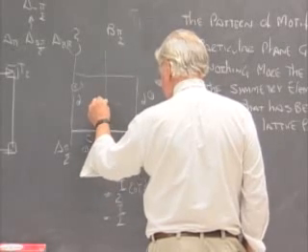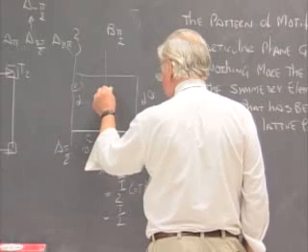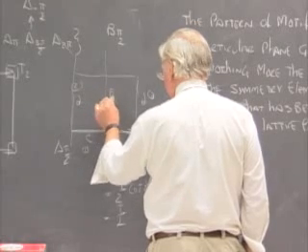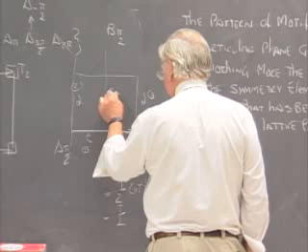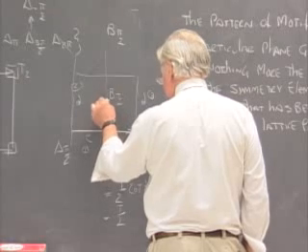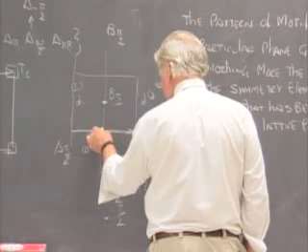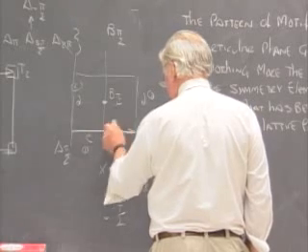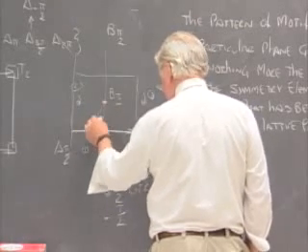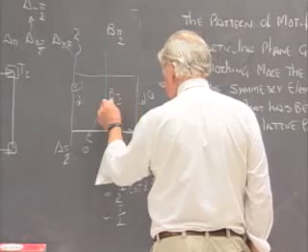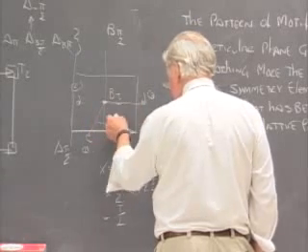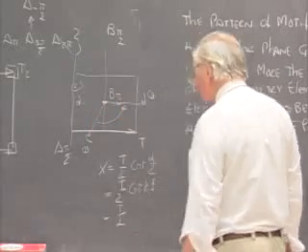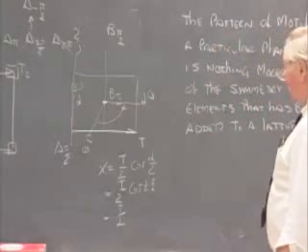And that puts me right in the middle of the cell. So the operation b pi over 2 sits not at the edge of the cell, but at the center of the cell. And that, I think you will agree, even in this hastily sketched diagram, is the way number 1 is related directly to number 3 in one shot.